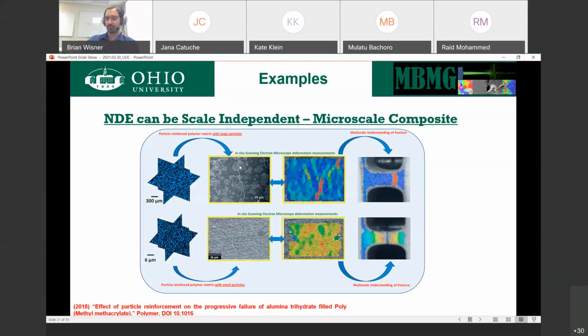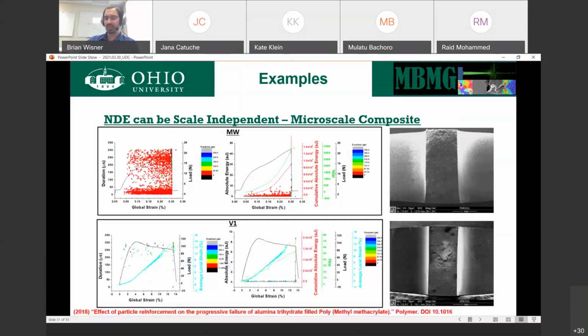Instead of particles fracturing, the material is growing around the particle. It's growing through the polymer. And AE shows that beautifully. Those where the particles fracture have a lot of activity going on. Those that don't, where you have the polymer failure, have very little acoustic activity. Knowing this, we have the possibility now of saying, well, clearly the smaller the particle, the more ductile we become. But we do so at the sacrifice of the load. We change the load. Can we alter these things?